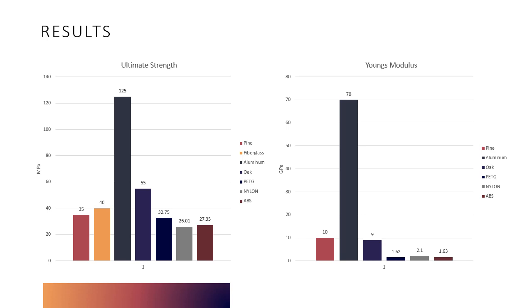Next are some comparative charts. They show the polymers I tested against wood, fiberglass, and 6000 series aluminum, and you can see that the polymers stack up pretty well, especially the PETG, against your lighter woods and your fiberglasses, but they do poorly against aluminum, which is to be expected. I wasn't overly surprised by these results.